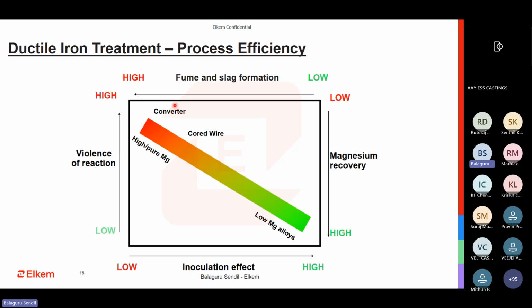We have pure magnesium converters, not the George Fischer. These are used for certain applications. Then we have cored wire, then we have sandwich, then we have tundish, and then we have in-mold. So you can see the in-mold is the most efficient way of doing ductile iron treatment. But the drawback is that all the castings need to be inspected 100%. Few foundries are doing it in India, but there's quite a strong demand for that in the American market, and American foundries are actually using a lot of in-mold FSM. When it comes to tundish, with a proper pocket and a tundish cover, it is one of the ideal ways where you can have very low reaction violence, high magnesium recovery, and very little slag and fume generation.